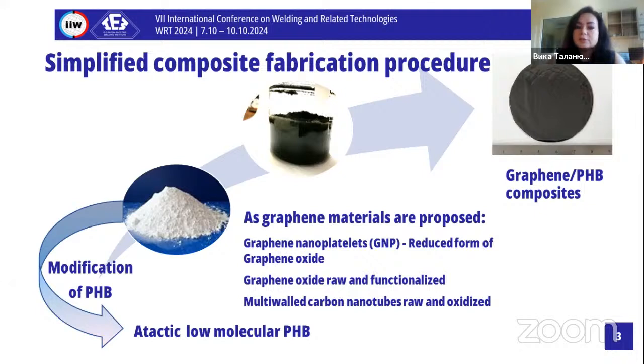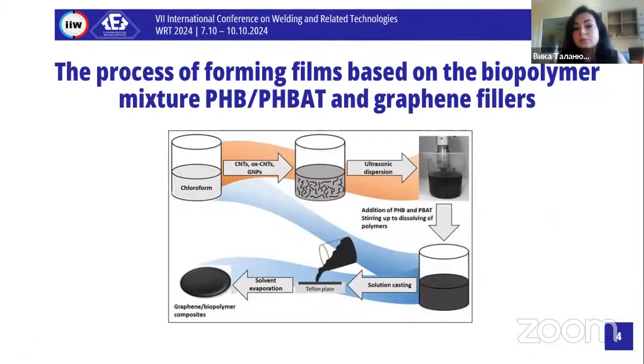We use the GNP, CNTs, and make some functionalization of graphene oxide. So we use some kinds of different materials in our films, and we get a graphene with polyhydroxybutyrate composite. It fills our materials for our sensor. You can see the procedure, how it looks in our methods. We start by preparing a normal classical solution casting, using ultrasonic dispersion for the nanotubes, and at the end of this process we get our films.